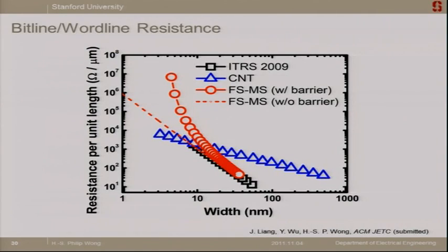All right. So this is the resistance per unit length of the wire versus the width of the wire, assuming a unit aspect ratio wire. This is the ITRS expectation. This is the models for wire, with and without a barrier, and it looks like this. And you can see that it rises very quickly, and that causes a tremendous problem, because if you want to build a memory array of a certain array size, then you have wire resistance, you need to drive current through the wire, then you have an IR drop, and pretty soon you don't have enough voltage to write the cell. Right?